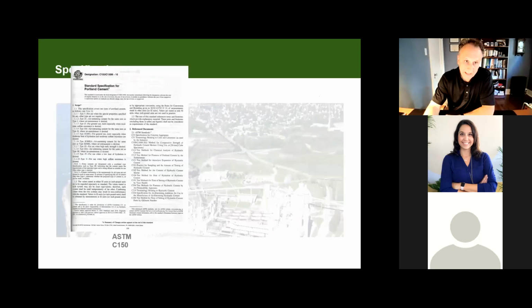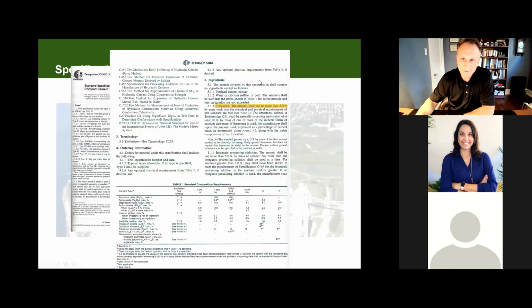It means that ASTM C150, for 10 plus years or so, has allowed 5% of ground limestone to be introduced into that 1 ton of clinker. So you can see right here, limestone, the amount shall not be more than 5%. So by doing that, we've been able to reduce the CO2 output at our plants by 5%. You make 2 million tons, you've been able to decrease your CO2 output by 5%.